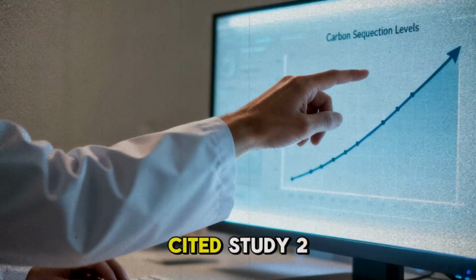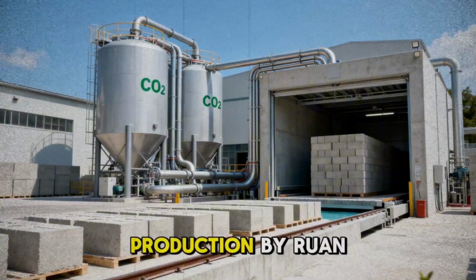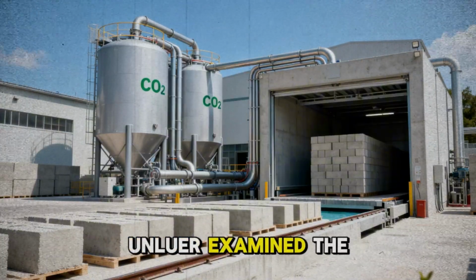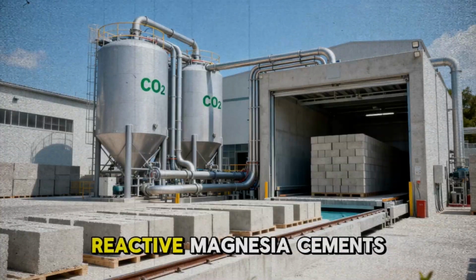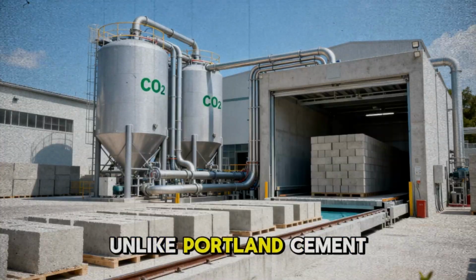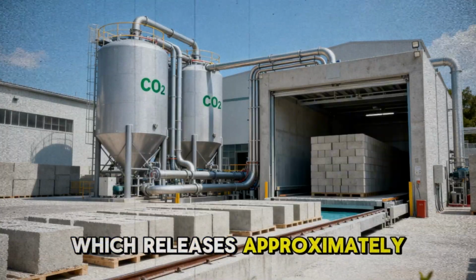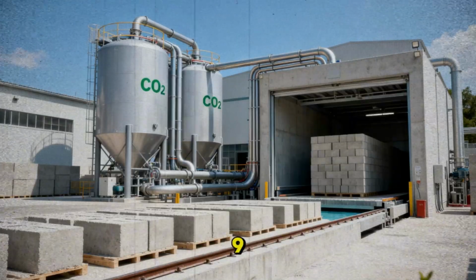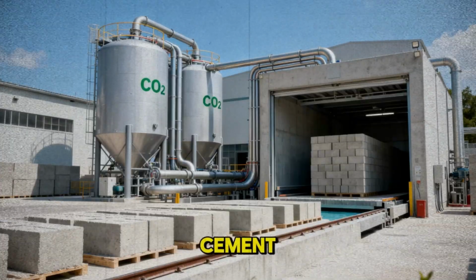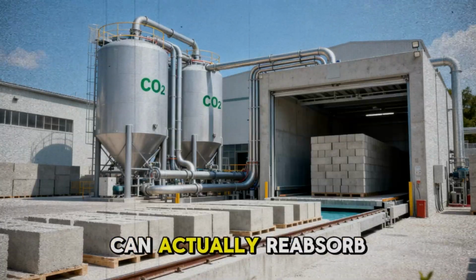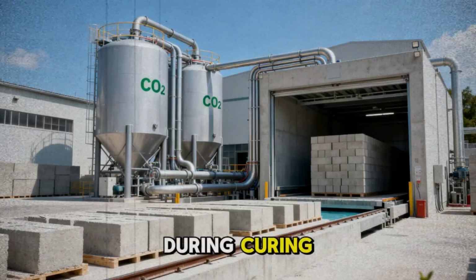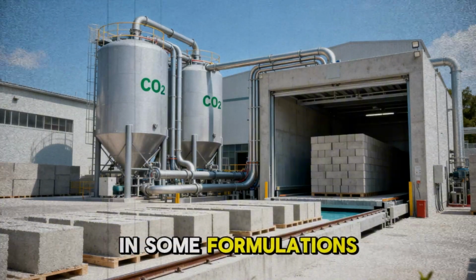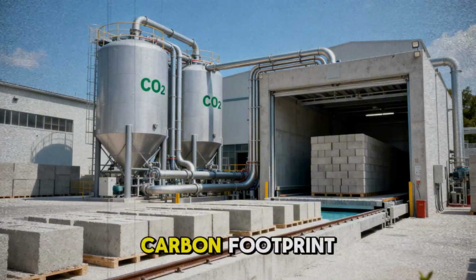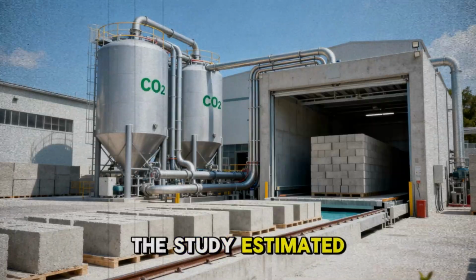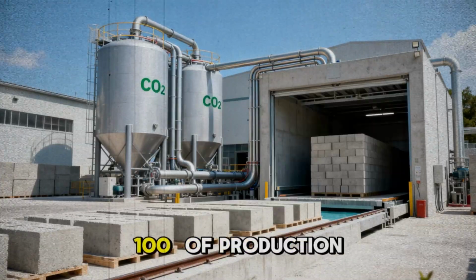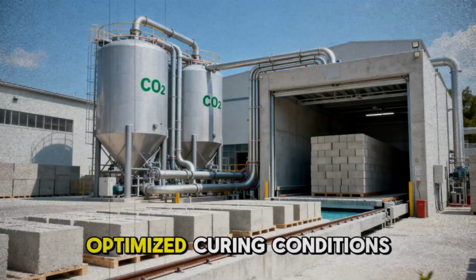Cited Study 2. A 2017 study in the Journal of Cleaner Production by Ruan and Unluer examined the carbon sequestration profile of reactive magnesia cements. Unlike Portland cement production, which releases approximately 0.8 to 0.9 kilograms of CO₂ per kilogram of cement produced, reactive magnesia can actually reabsorb CO₂ during curing, partially offsetting, or in some formulations, nearly eliminating its production carbon footprint. The study estimated net CO₂ absorption of up to 100% of production emissions under optimized curing conditions.